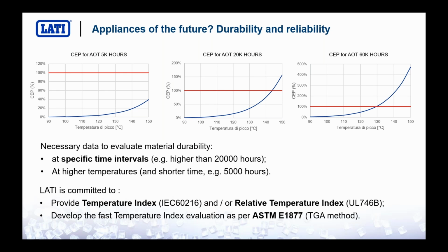So we are committed to provide the temperature index or the relative temperature index obtained by UL. And we are also working, this is very important, to develop the ASTM E1877 method, which is a very fast method using thermogravimetry to evaluate the temperature index. It is not the same as the above, but at least it is very, very fast. You can have a temperature index in just a few hours, but this method is still under development. And we are trying to understand how reliable it is and to introduce it in our practice.